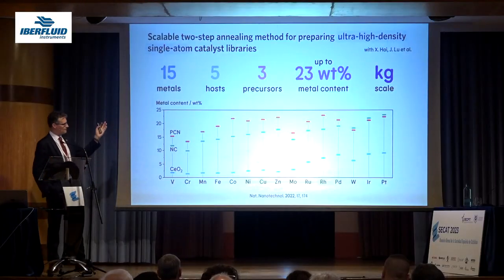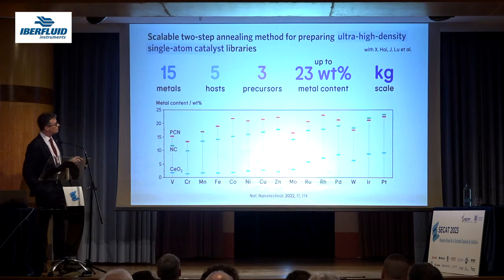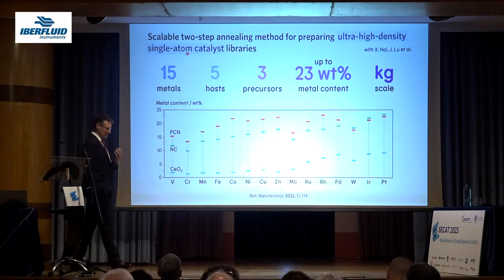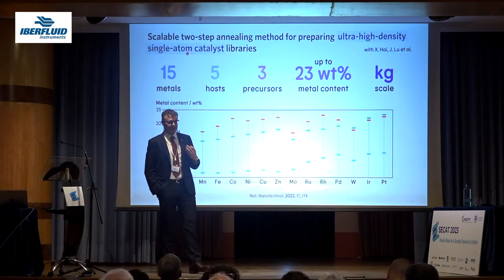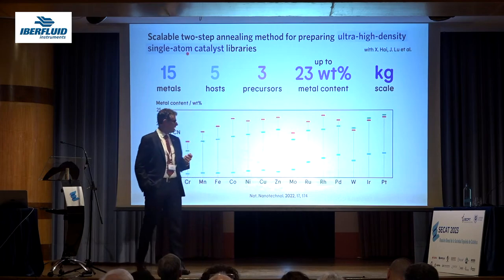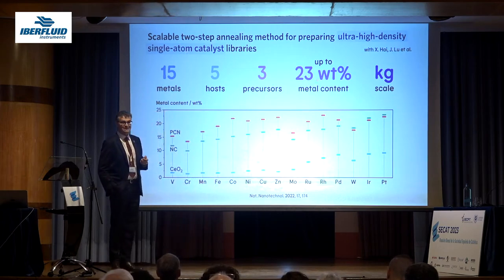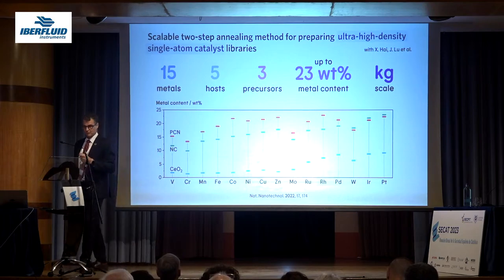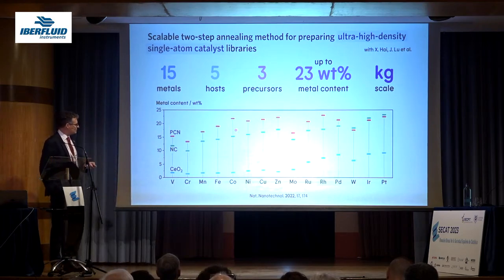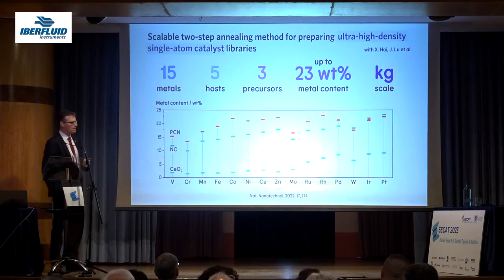I'm not going to describe, because of lack of time, the recipes. But we solved this problem of making what we call ultra-high density single atom catalyst. So these are catalytic materials which display isolated metal centers where the loadings can reach as much as 23% of metal. 23% of metal. And of course, these high loadings are typically obtained on carbon support. So here is nitrogen-doped carbon, and this is polymeric carbon nitride. You see, for many different metals, you could systematically obtain very high loadings.